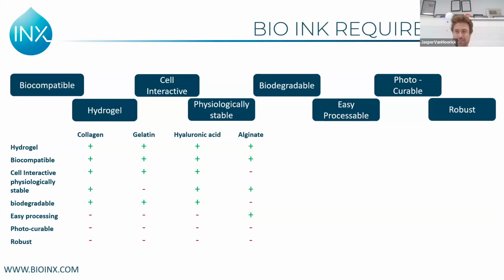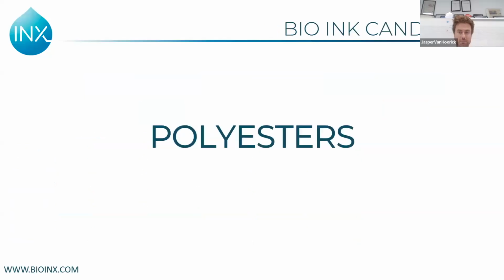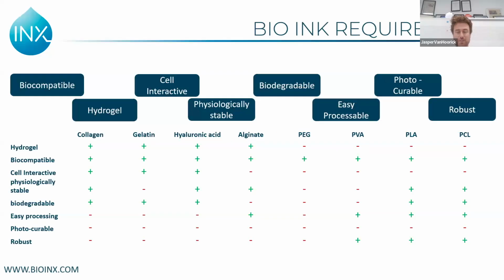So let's look at the usual suspects in synthetic ones. Polyethylene glycol is a very popular hydrogel with a large track record in the biomedical field. And polyvinyl alcohol is used a lot. Polyvinyl alcohol is a material which is used a lot in 3D printing, mainly for sacrificial materials. But again, we see that they're not doing great. So maybe we need to look at other material classes, what's typically used in the field. And polyesters can also be interesting. Why polyesters? Because if you think about 3D printing, they are very popular materials and they are biodegradable and they are biocompatible. Some of them are polylactic acid and polycaprolactone, for example. So we already have a whole array of materials where we can start from, but we see that none of them ticks all the boxes.